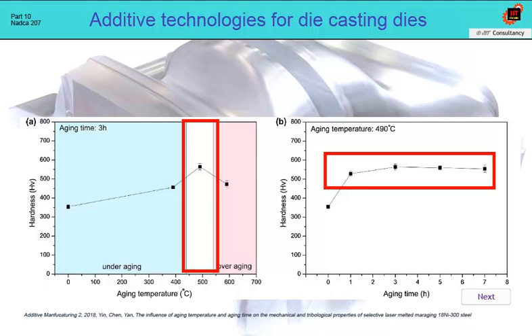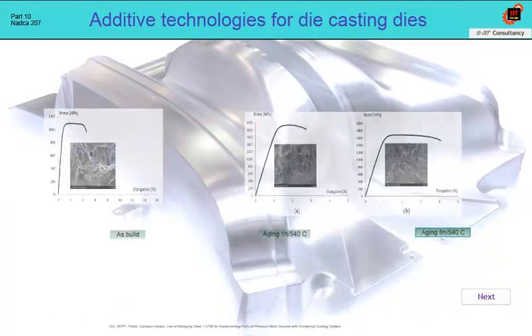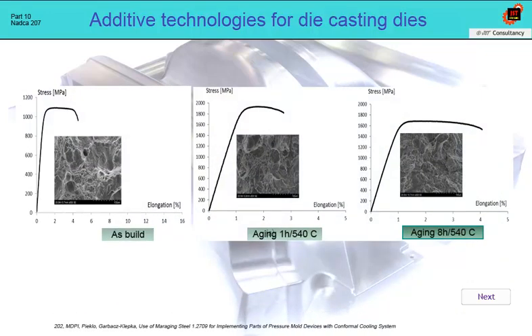How the mechanical properties of steel change can be seen in the following diagrams from tensile tests after printing, after aging for 1 hour at a temperature of 540, and after aging 8 hours at the same temperature. The precipitation hardening process increases the tensile strength, reduces the ductility of the steel.